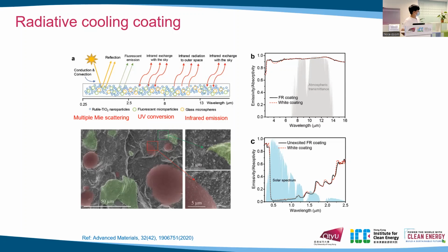We can see in the SEM image that all the particles are well dispersed in the polymer matrix. With all the help from these fillers, our coating can achieve infrared emissivity as well as solar reflectance, both over 90%.